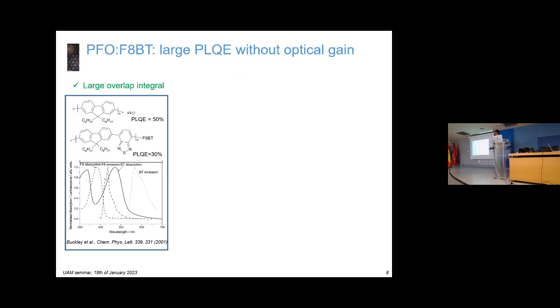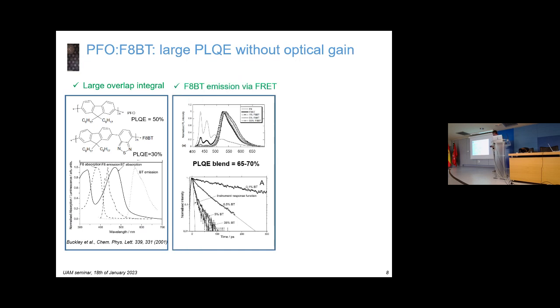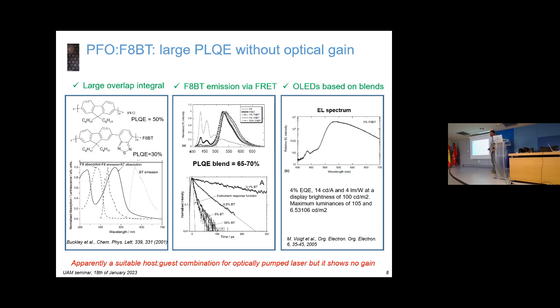So this one is PFO, and this one is F8BT. The thing about these two is that you can blend one with the other, and because of the resonance conditions, with very little amounts of F8BT in PFO, you will drive the emission very efficiently from blue to yellow. You can see this also if you monitor the luminescence dynamics of the host PFO polymer. The efficiency is really high, it shoots up to 70%. On top of that, because the two polymers have good transport properties, you can make nice polymer light-emitting diodes.